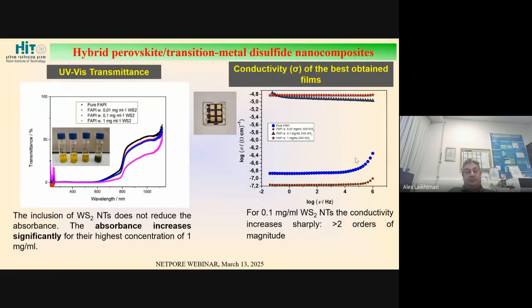And for example, our colleagues, the group of Andrea Gajovic in Zagreb, prepared the mixture of the FA perovskites, formamidinium perovskites, with different concentrations of WS2 nanoparticles. Here you can see the concentration. They measured the transmittance, and they see that there is some increase in the absorbance for the high concentration of nanoparticles. On the other hand, they also produced a kind of device to measure the conductivity for different concentrations.